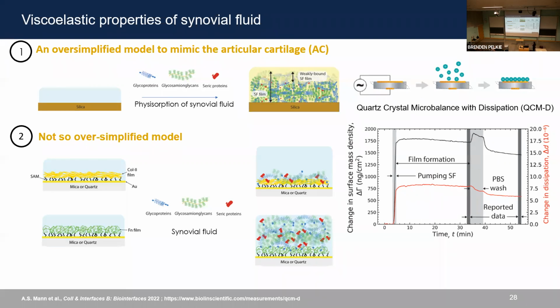And the graph on the right is showing the typical trace of an experiment using QCMD. Here on the left side, the change in surface mass density is plotted with real time. We first establish a baseline with phosphate buffered saline, and then as we are adsorbing synovial fluid components, the change in surface mass density increases, and we then perform a washing step in order to take away the loosely bound molecules from the thin film.